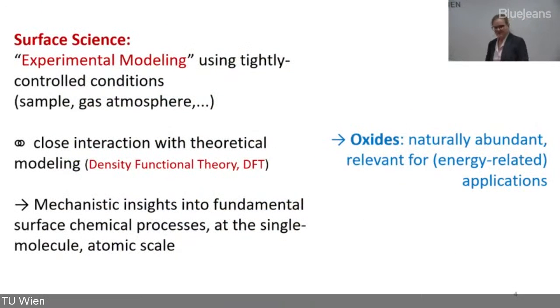Gerhard Ertl pioneered the surface science method. My take on surface science is experimental modeling using tightly controlled conditions: very specialized, well-defined samples, and very well-controlled gas atmospheres. Because of these well-controlled systems, there's a very close interaction with theoretical modeling, specifically density functional theory, where people can calculate slabs at 0 Kelvin in a perfect vacuum. Because both systems are so well controlled, there's a very tight interaction between experiment and theory.